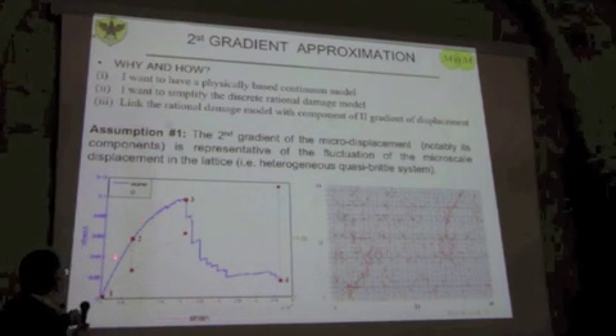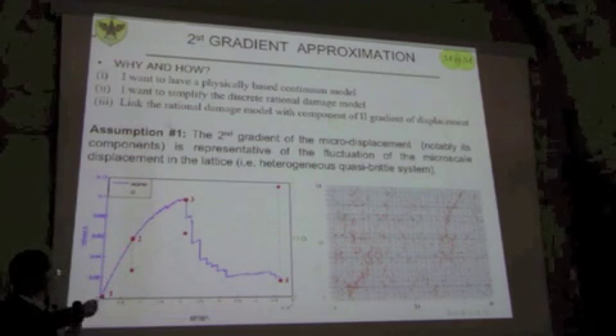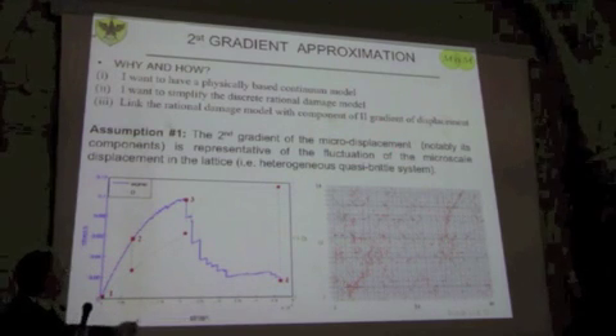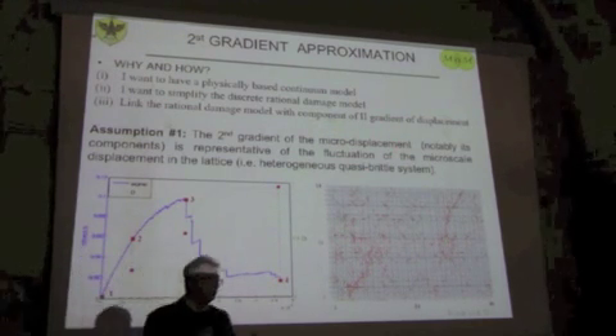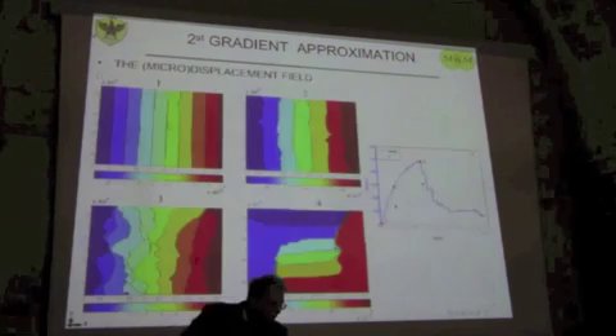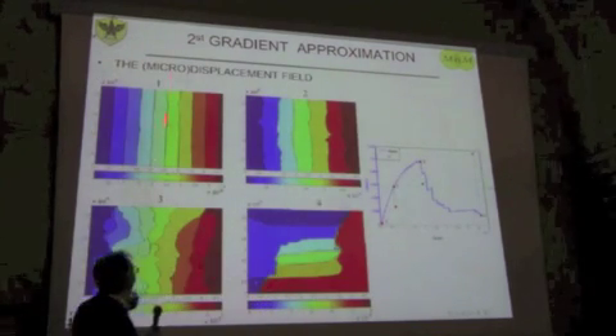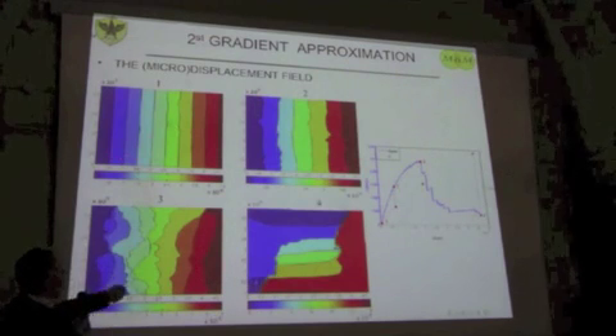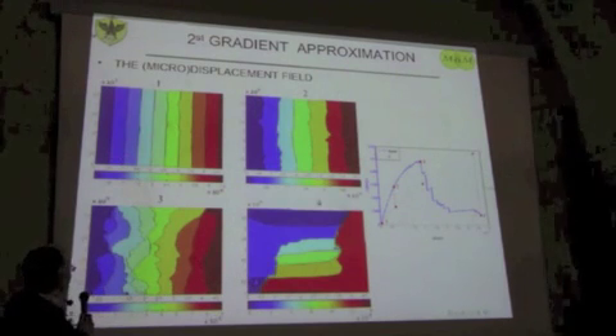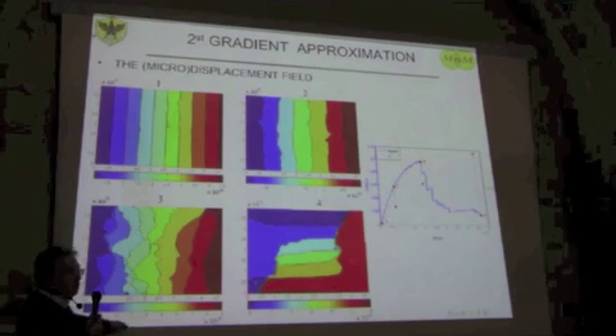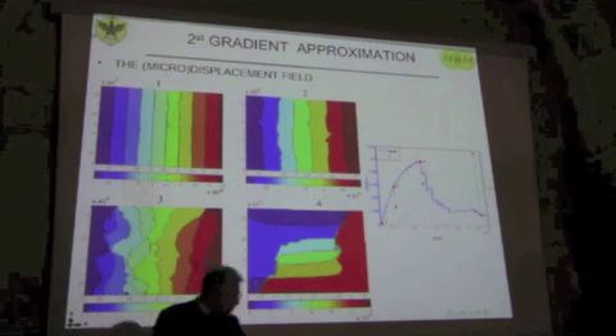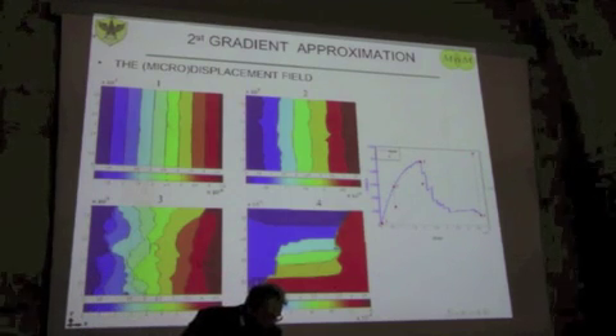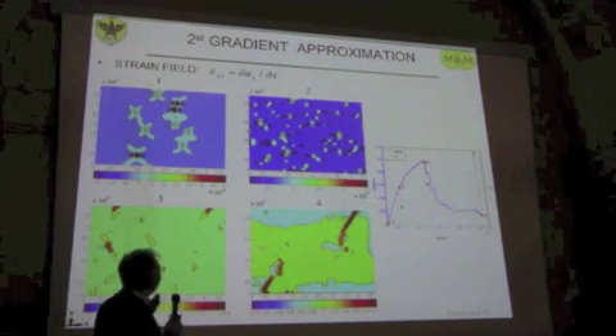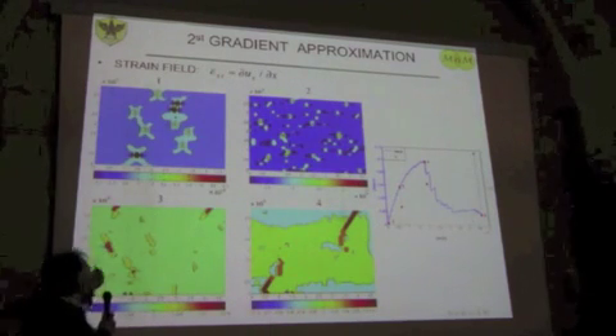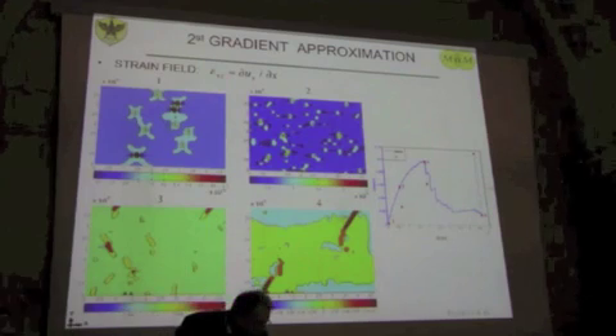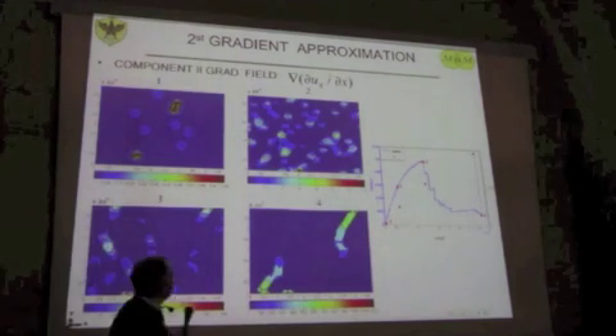This is the response. I'm going to check 4 points. This is a grid where I actually measure the strain field with the digital image correlation technique. I'm going to show you what happens in the beginning when I have no damage, when I have some damage, when I am at the peak, and when I am at the failure. You can definitely see that the displacement field reveals the whole story. Then I'm checking the strain, so the first derivative, the first gradient, and then the second gradient.